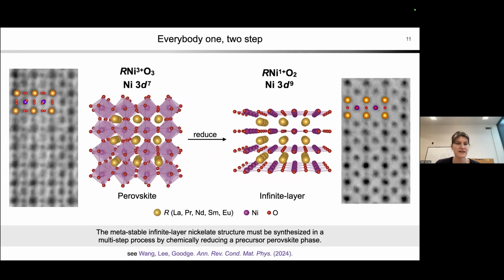So one of the key breakthroughs that came several years ago to allow this possibility is the idea that you first grow a more stable nickel compound in this d7 configuration. You can see a comparison of the atomic structures. And then you perform a chemical reaction to actually extract some of those oxygens. If you look at the chemical formulas on the top, you go from a rare earth nickel O3, you take out 1/3 of those oxygens, and you end up at rare earth nickel O2.